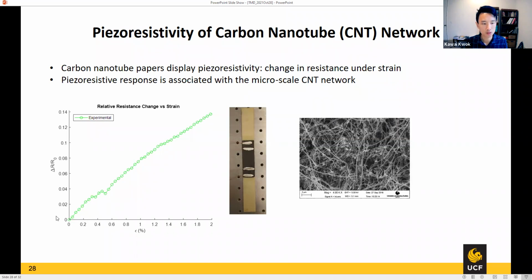But you see the resistance change versus the strain. We actually went up to even higher strain than 2%, and you can get a pretty sensitive strain response. So this is quite a good strain sensor that we can put on because it's thin, so it's good for a thin-ply composite. You can go to high strains without breaking at all. So these are the sort of high-deformation, high-shape-change structures where this would be relevant.